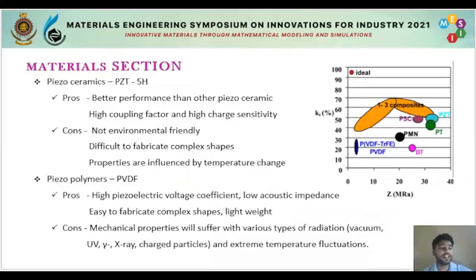Let's move to the material selection. Here we have chosen our material based on several factors such as electromechanical coupling coefficients, acoustic impedance, and so on. The first material we have chosen was piezo ceramics. Particularly, we have chosen PZT5H, which is a metallic oxide that has a perovskite crystal structure, which can offer high permittivity, high coupling factors, and piezoelectric constants.